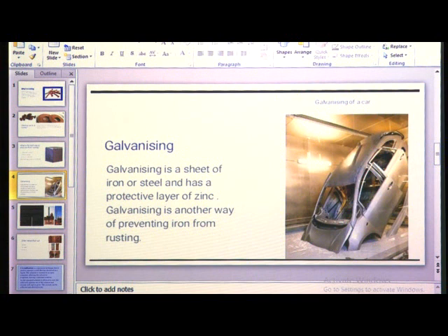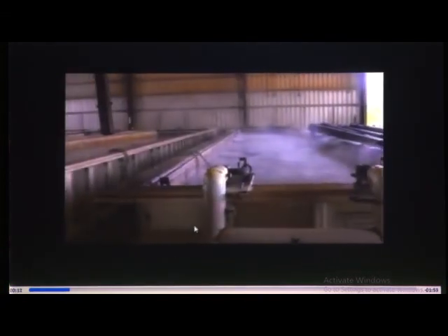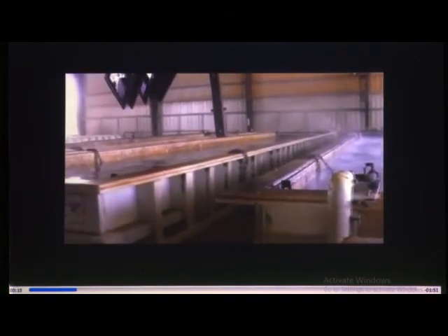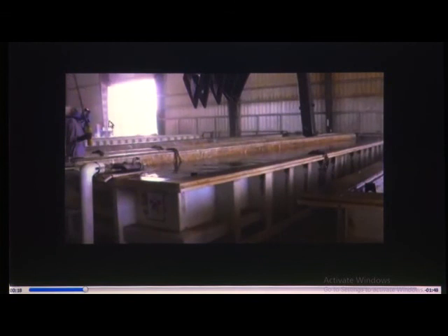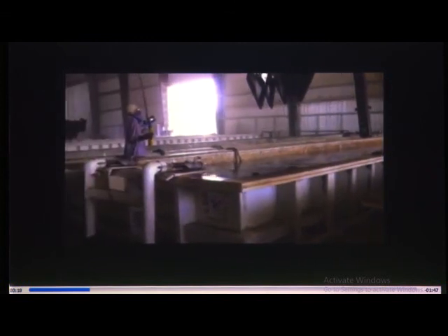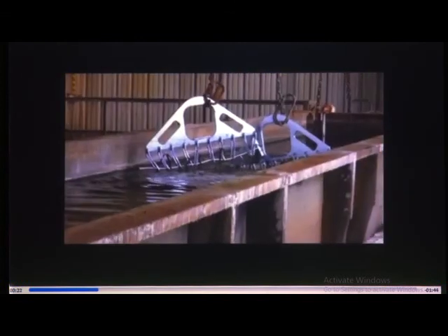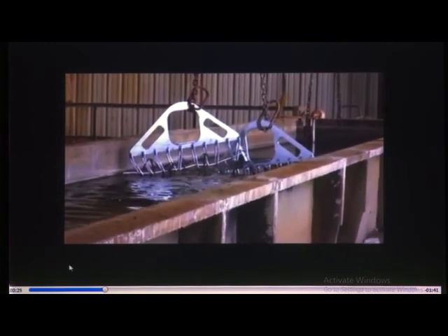factories or industries. Hot dip galvanizing is achieved by immersing clean steel products in molten zinc at 830 to 850 degrees Fahrenheit. But before the steel can enter the galvanizing kettle, it must go through a 4-step cleaning process. So here you can see some tanks are there. Okay. So some rectangular tanks are made up here and which are filled with some solution. Yes. The steel first enters the caustic tank at 180 degrees Fahrenheit in order to remove paint residue. It's then rinsed in a fresh water tank.